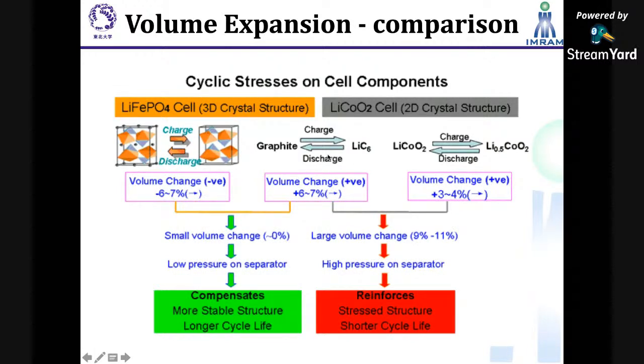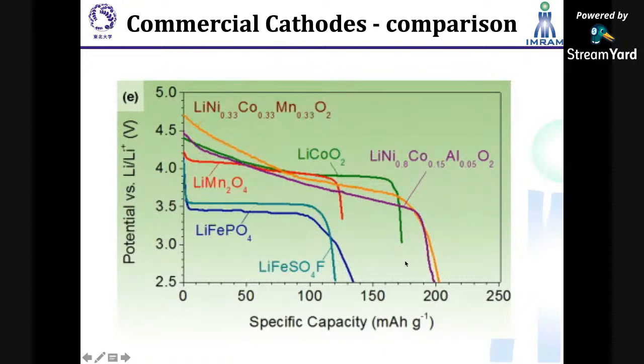Therefore, combining this with lithium carbon, the volume change becomes zero. If you make a battery based on this, it does not have any volume change, and the performance of the battery is better compared to lithium cobalt oxide. To compare all the cathode materials developed at present, the present generation batteries, since 2016, mostly use lithium nickel cobalt manganese oxide. Still, there is no other cathode material which shows zero volume expansion or no structural change during charging and discharging, other than lithium iron phosphate.